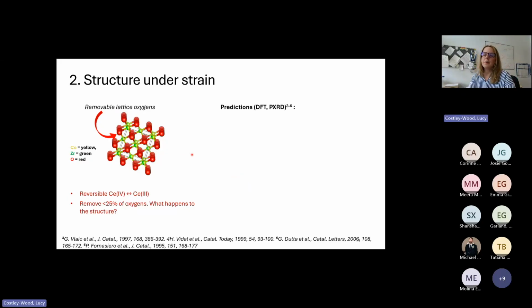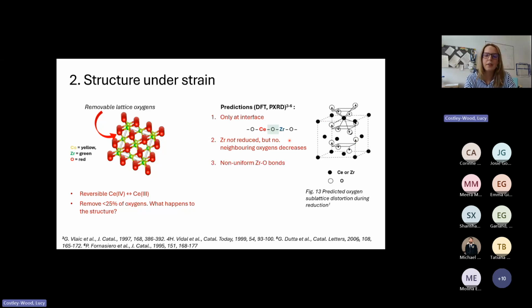Predictions from the literature, from particularly powder diffraction, ex situ powder diffraction, and DFT, is that firstly, the oxygen which is removed from the structure is only at the interface between a cerium and a zirconium. Secondly, the zirconium is not reduced, and that kind of fits with zirconium's behavior, but the number of neighboring oxygens decreases. And when this happens, we get non-uniform zirconium-oxygen bonds.